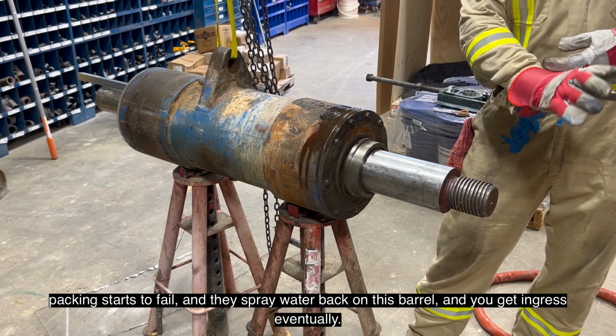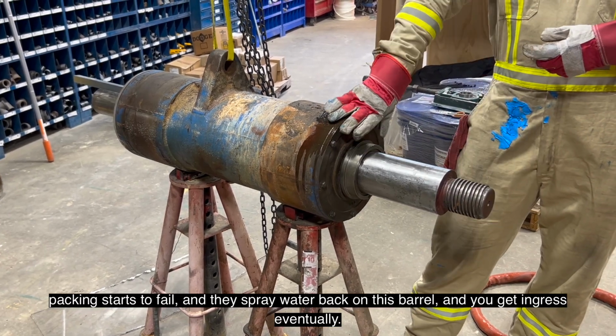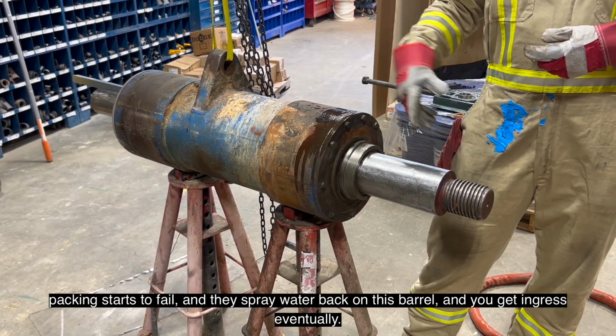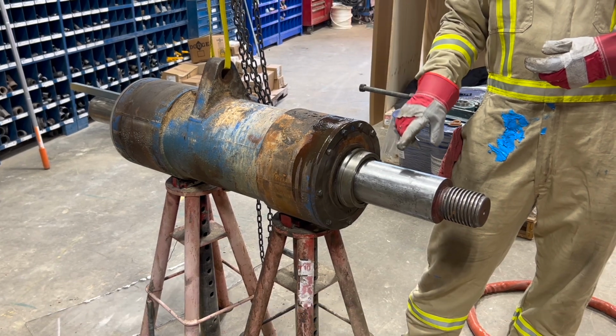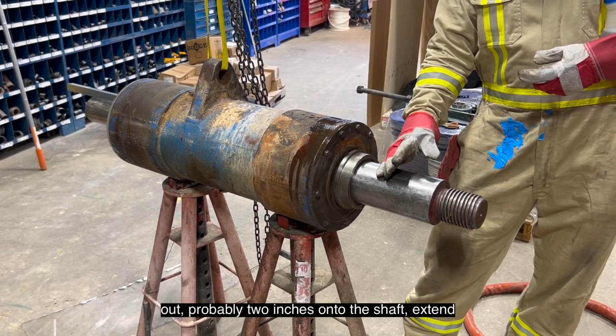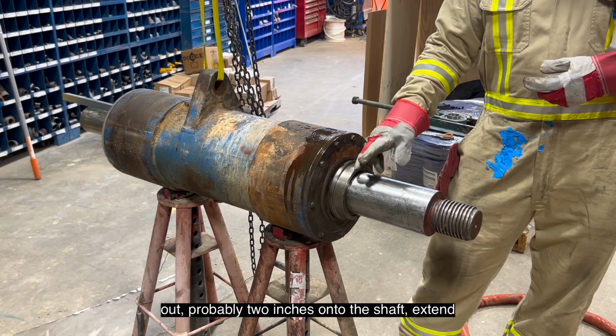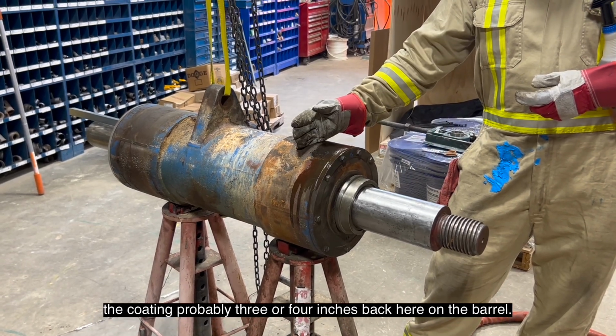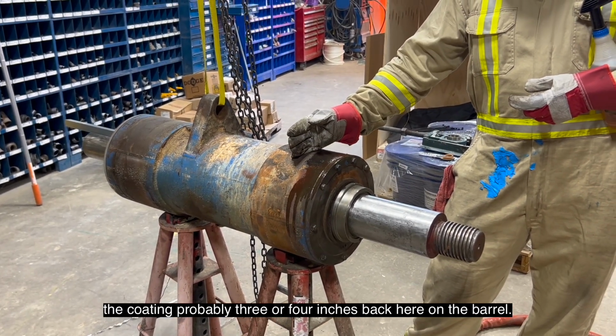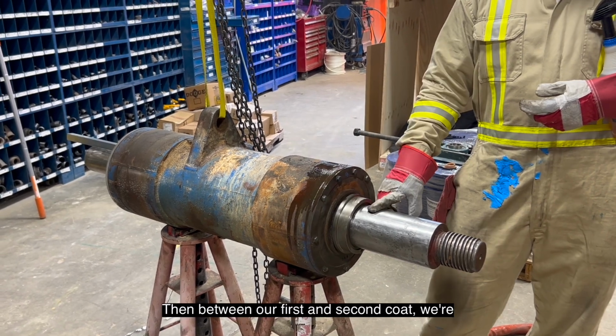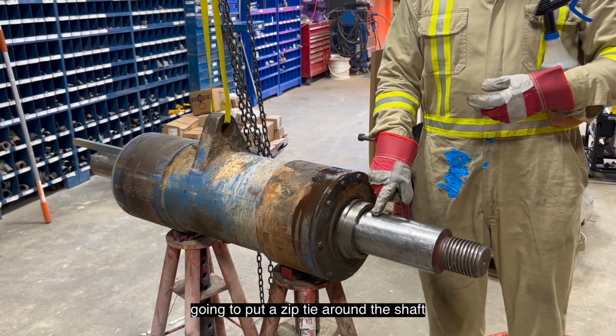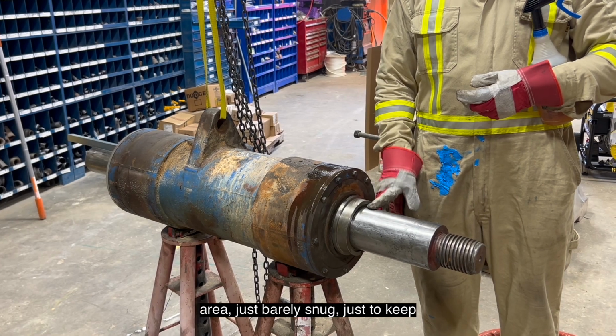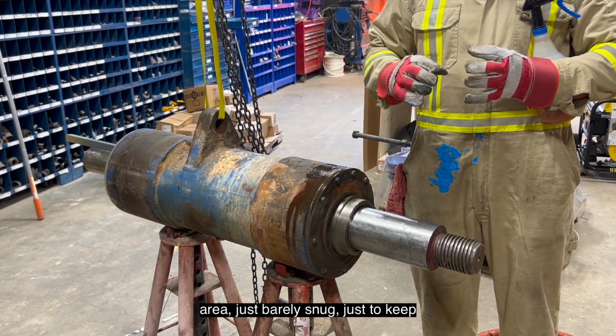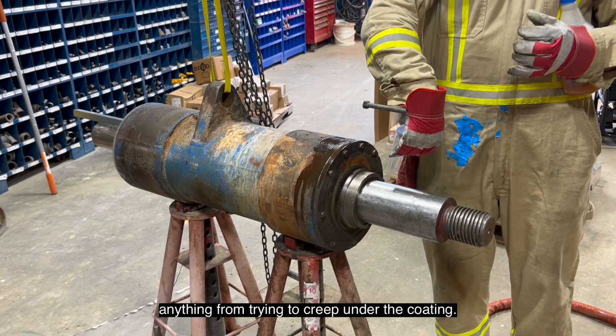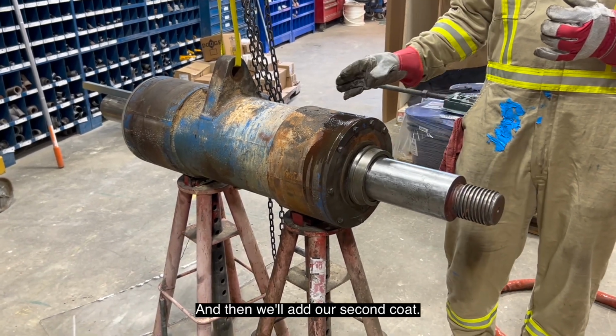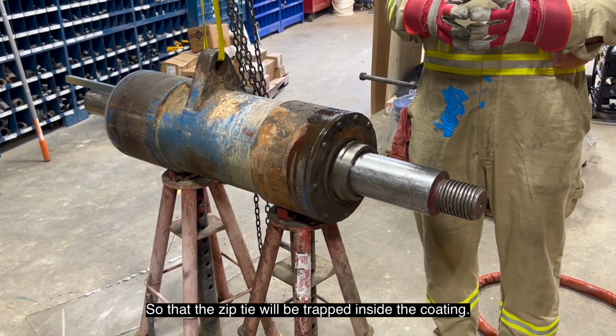Packing starts to fail, and they spray water back on this barrel, and you get ingress eventually. So we're going to coat out probably 2 inches onto this shaft, extend the coating probably 3 or 4 inches back here on the barrel. Then between our first and second coat, we're going to put a zip tie around the shaft area, just barely snug, just to keep anything from trying to creep under the coating. And then we'll add our second coat. So that zip tie will be trapped inside the coating.